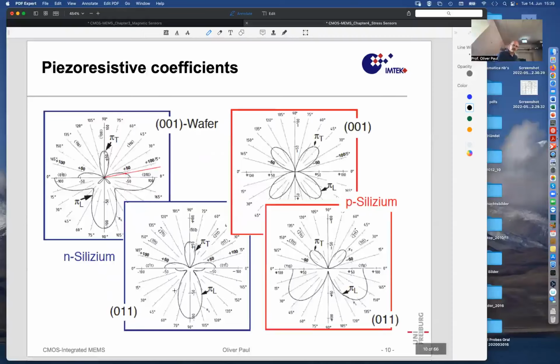So when we apply these transformation laws, this is a graphic that I took from my semiconductor lecture. We see that pi longitudinal is orientation dependent, and therefore designing a sensor requires a bit of thinking. So what we see here is the number of minus 100. It's written here minus 100. Well, it depends, which curve this refers to. So the top curve or the bottom curve. So let's consider this pi longitudinal. This direction is a 100, is the 100 direction. This direction is the 010 direction.